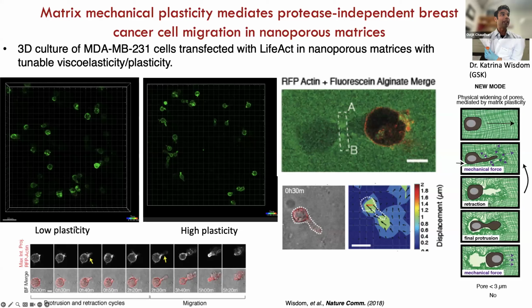And what you see is in the low plasticity matrices, cells stay rounded. They don't really do a whole lot. Whereas in the high plasticity matrices, some substantial fraction of cells are able to migrate quite robustly through the matrix.